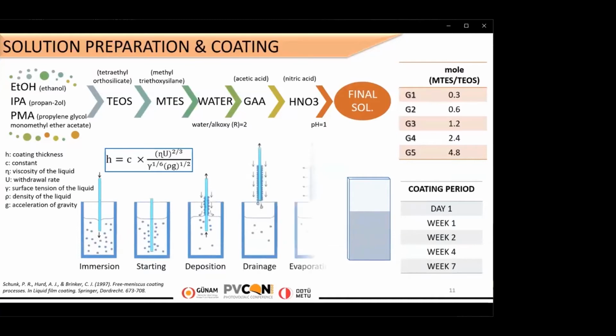The substrate is immersed into the solution. The substrate which has been dipped into the solution starts to be pulled up. The withdrawal is carried out at a constant rate. The film is deposited on the substrate while it's pulled up. The solvent is evaporated from the deposited liquid film, resulting in the coating.